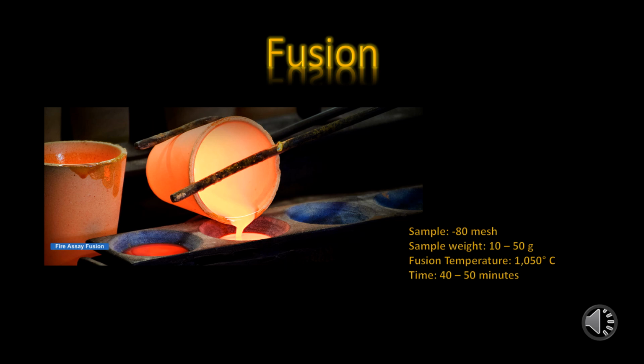This melt is then poured into cone molds for cooling, which forms a solid mass consisting of gangue material and a lead button, which contains the gold and the silver and any present platinum group metals. The lead button can then be easily removed from the slag for further processing. Although this process is simple in concept, the procedure is a little more complex and will be discussed in a future presentation.